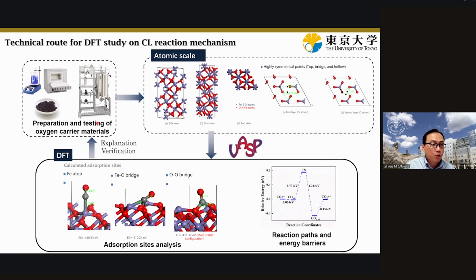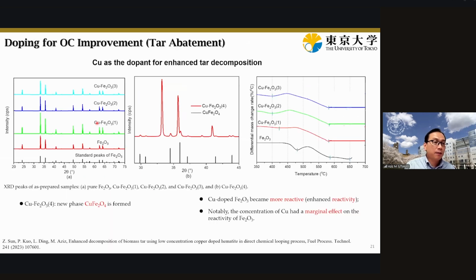to clarify this. For the doping itself, our PhD student has also done research on copper doping over the years. And we could see that by doping even a small amount of copper, the copper-doped iron oxide, or hematite, is much more reactive compared to the normal Fe2O3 itself. So we could see over the years that the reactivity has increased well.